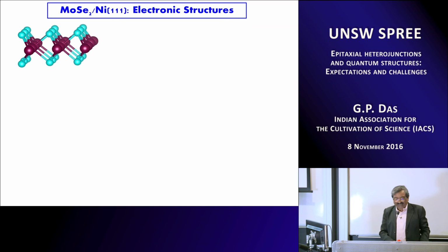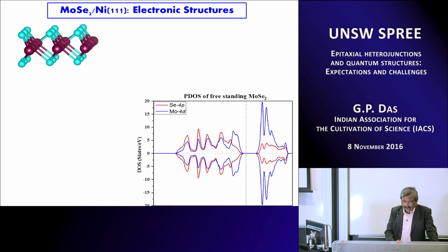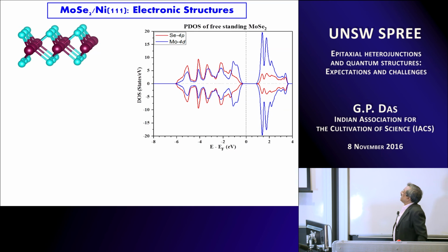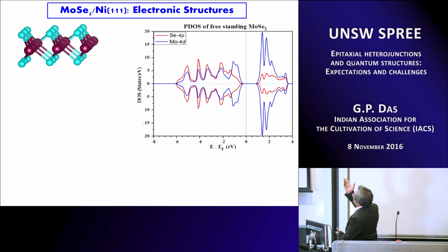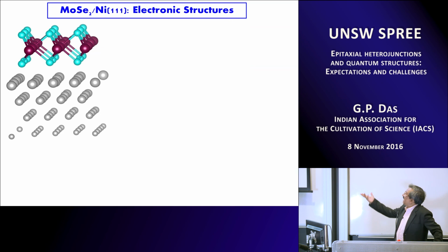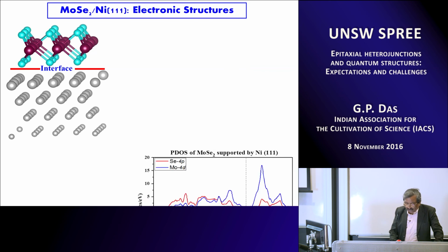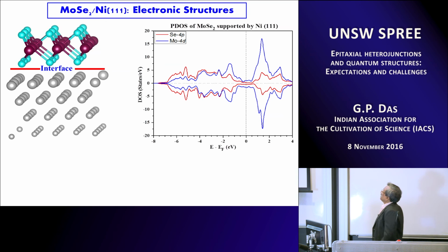And the electronic structure shows a very interesting thing. When you do it on a monolayer MoSe2, this is how the density of states looks. You can see the red one is the partial density of states of selenium, and the blue one is the partial density of states of molybdenum, and you can see an LDA gap which is obvious. Okay, MoSe2. Now what I do is that I put a nickel 111 substrate, and this is the interface between MoSe2 and nickel 111. Now lo and behold, what happens to the density of states?